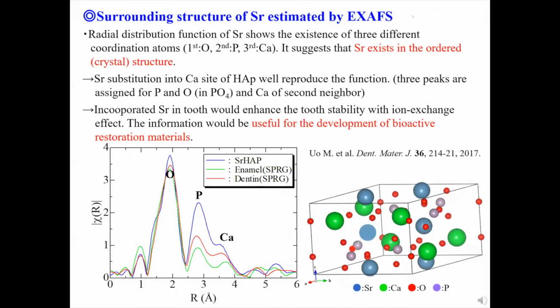This figure shows the radial distribution function of strontium. The center atom is strontium and the x-axis means the distance to neighbor atoms from strontium. The y-axis is the coordination number of neighbor atoms. Green is the result from the strontium-absorbed enamel and red is from dentin. The blue line is the reference, synthesized strontium apatite.